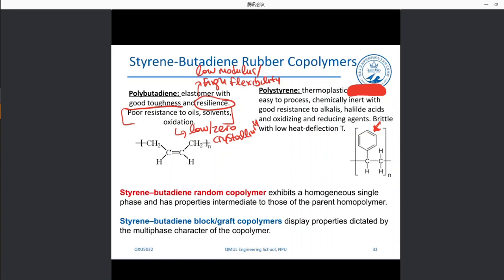However, mechanically it is very brittle. Because it is brittle, it shows high modulus and low elongation. Usually the modulus of polystyrene is around 3 gigapascals. So usually we create styrene butadiene random and block copolymers. The random copolymer shows a single phase, so properties intermediate to those of the parent homopolymers.